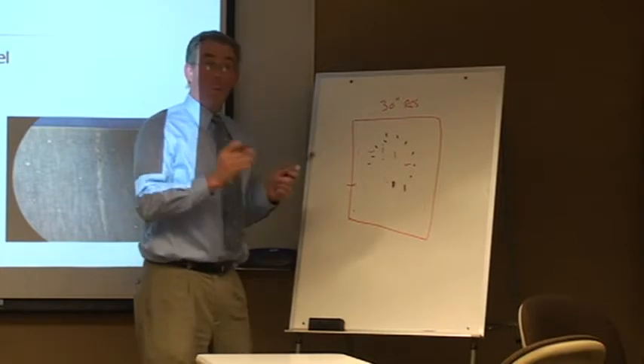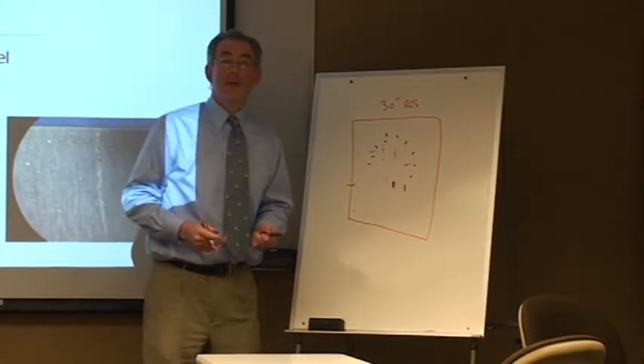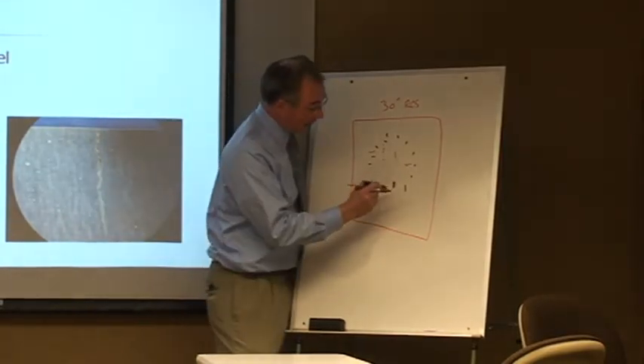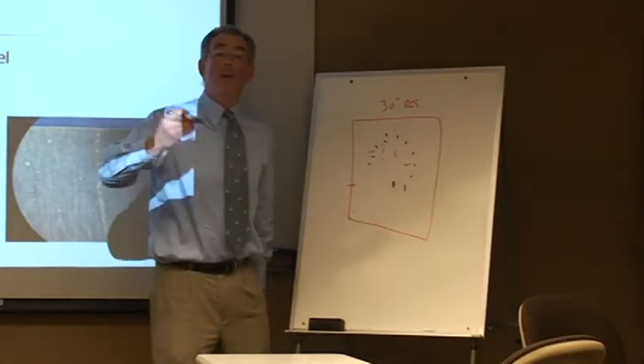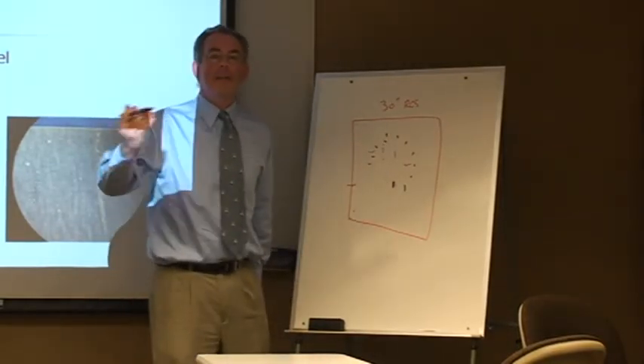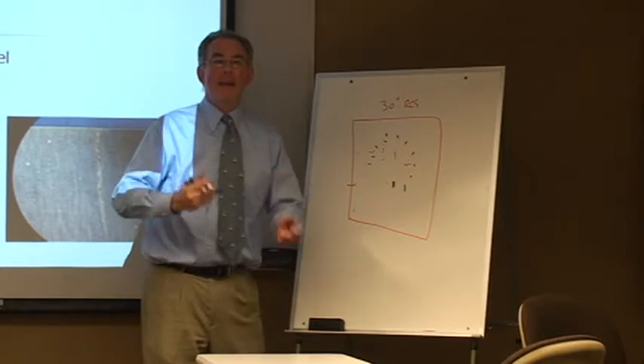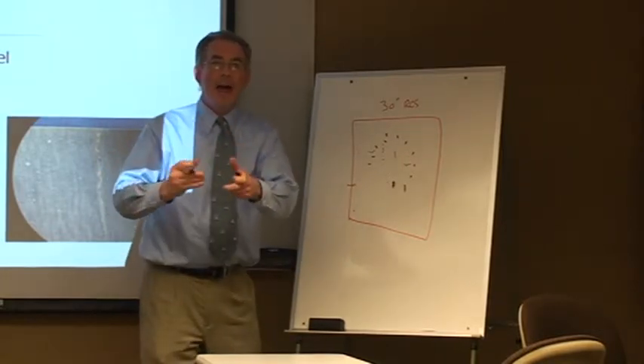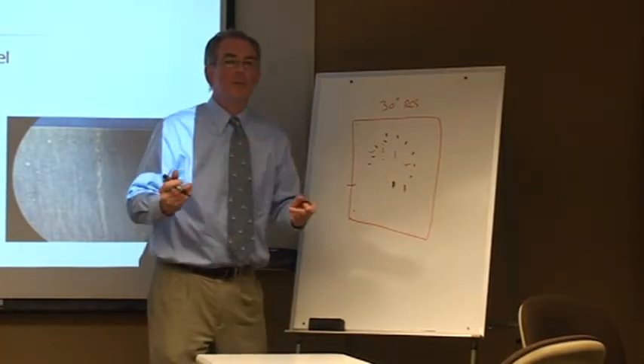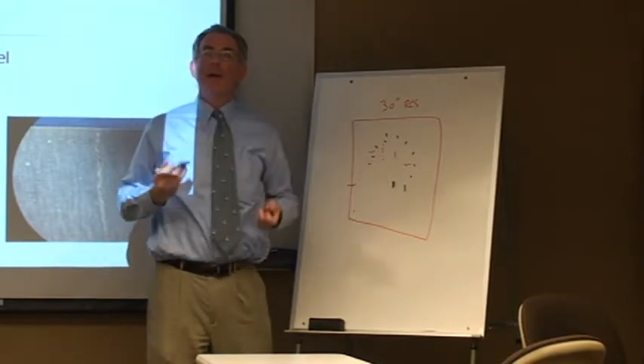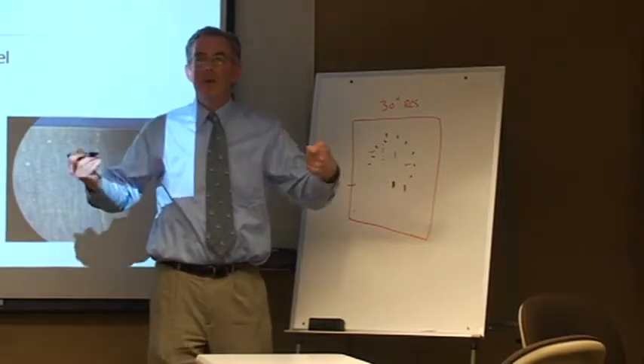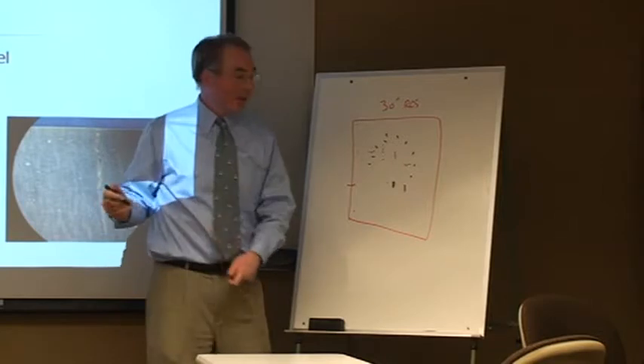Ways to avoid it. One way is we put sulfur in the steel. Which will create manganese sulfides, relatively harmless inclusion. Matter of fact, some people like to have sulfur added for these manganese sulfides because it helps the machinability of steel. Many of the grades we make for Scott Forge, we have minimum sulfur contents for machinability.